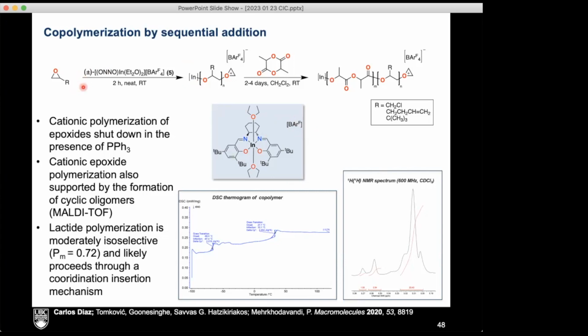And this is really cool because he's able to change the mechanism of the system for each of the monomers. So you can see that they're block copolymers just really quickly by looking at the DSC, et cetera, you can see the two different peaks. And what's really cool is that he's seeing an iso-rich polymer, which is what we would expect with the kind of ligand system that we have.